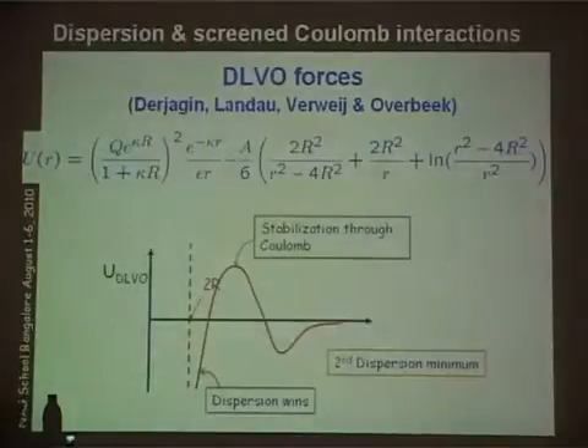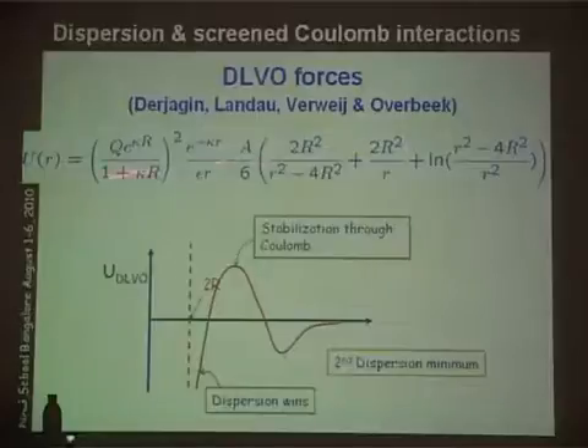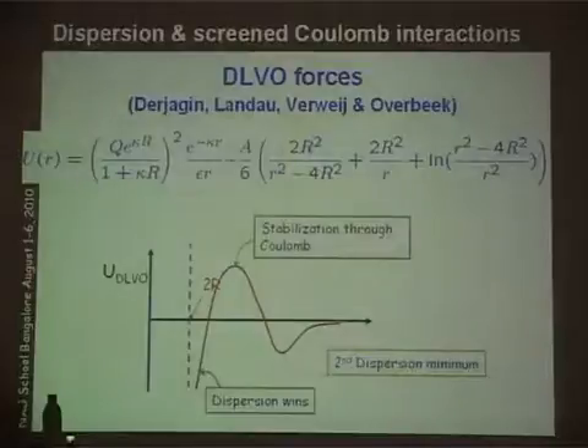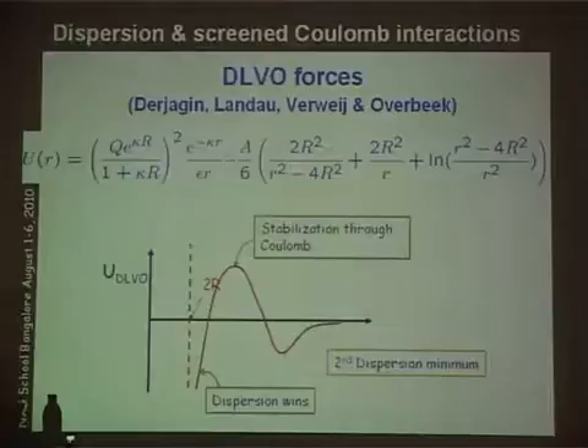Now, what is important is that very often in many systems you come across a combination of the two, dispersion and screened Coulomb interactions. They are also called DLVO forces after Derjaguin and Landau, both Russians, independently in the late 40s. There was also a publication by Verwey and Overbeek in the Netherlands, and they came up with this overall interaction potential between two particles that are both charged and have van der Waals attraction. And now, by playing with the added charge in the system, you can play with the overall interaction potential here.